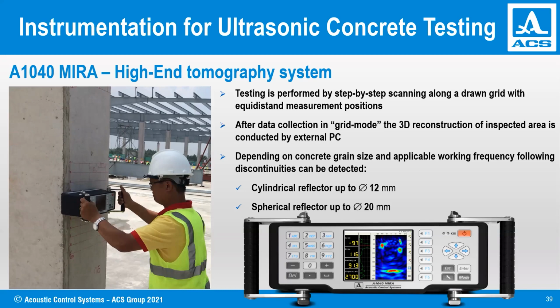But again, the very frequent question we get from inexperienced users is, what is the smallest defect I can find? Of course, I indicate some values now on the slide, but it always depends very much on the material. If we have a coarse grain material where we cannot apply higher frequencies, we have to reduce the inspection frequency to be able to penetrate at all. Of course, in this case our detection and resolution capabilities go down, and vice versa. If it is a very fine concrete, we can increase the frequency and improve our defect detectability. So we are always as good as the material allows us to be.